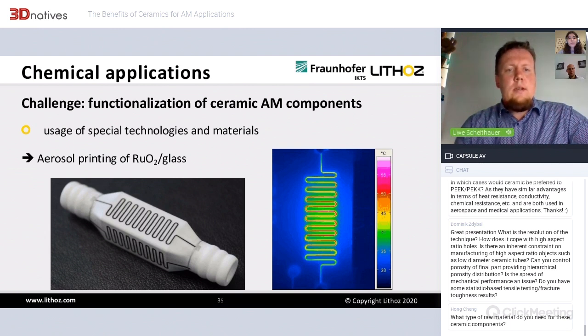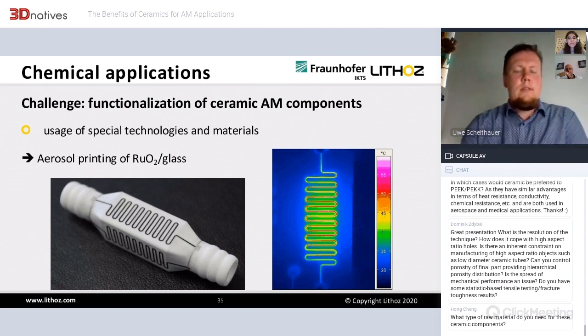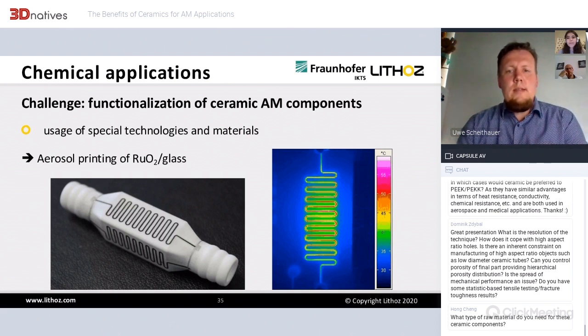The substrate was realized in alumina, and after sintering we used aerosol printing to realize this heater structure based on ruthenium oxide in a glass matrix. And here in this picture on the right side, you see that it can be used to heat up the whole component. And because of the complex structure inside, it's possible to transfer the heat from the outer surface to the fluid which runs through.